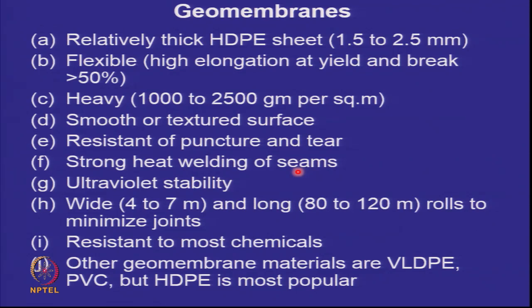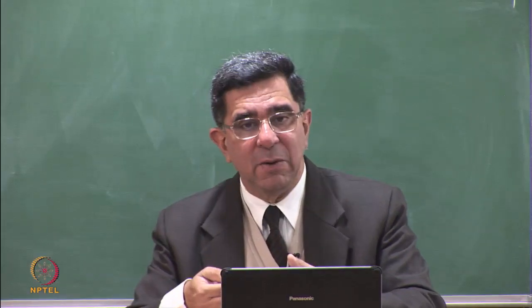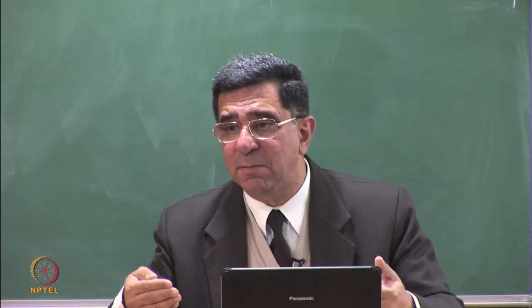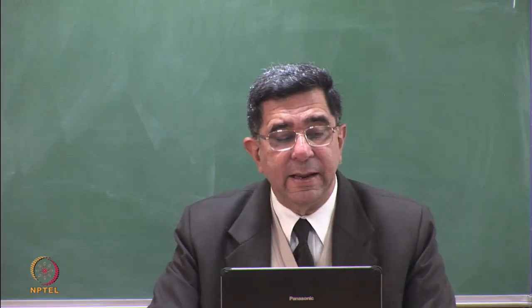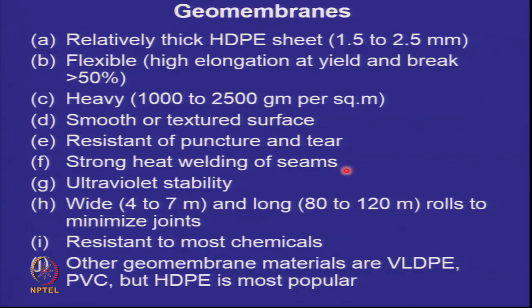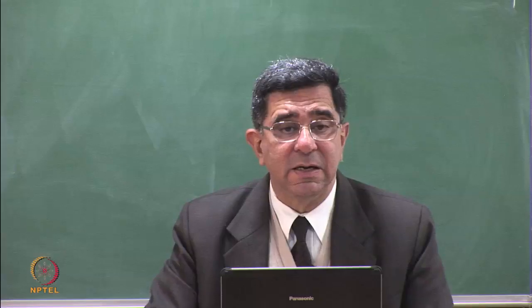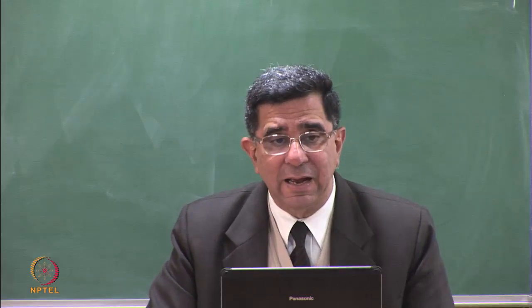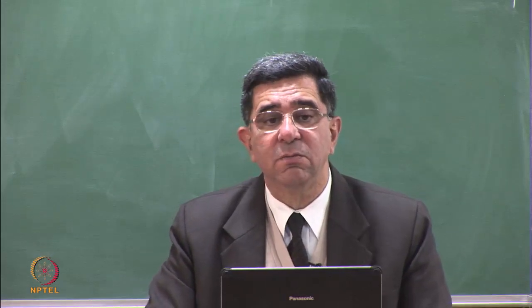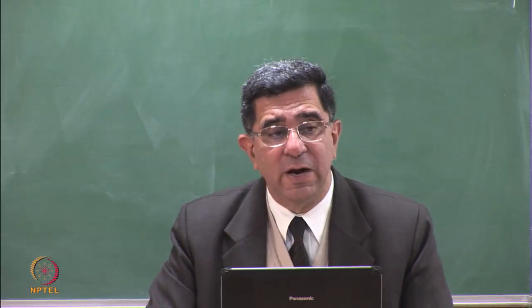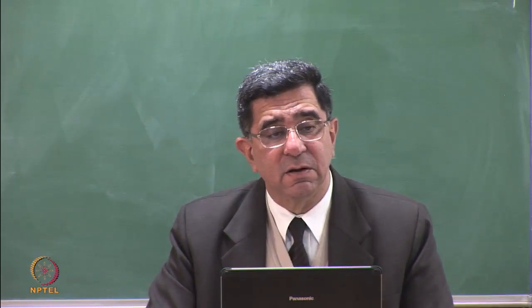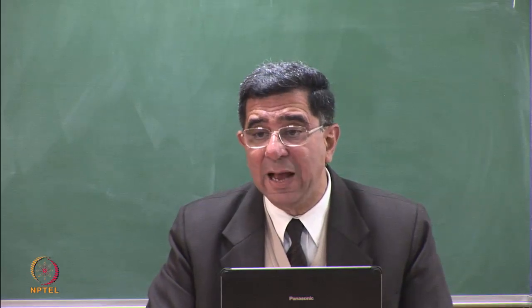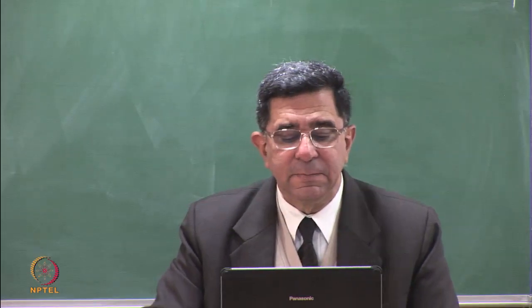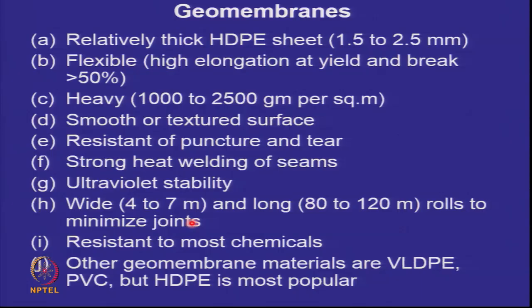When you weld something, you're always bothered. You have used thermal welding or you've added something. Is it as strong as the parent material? So in HDPE welding, you will see what is the quality control criteria. They have ultraviolet stability. Most of the time they look black because ultraviolet stability comes in polymers when you use carbon black. Carbon black gives you UV stability. So many of the overhead water tanks and many of the polymeric materials which look black are on account of UV stability. They can come in wide rolls.